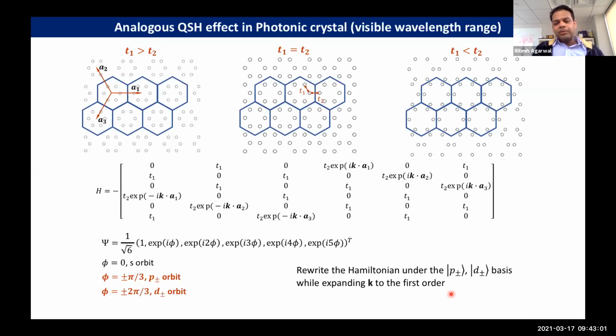in the photonics regime. So since we wanted to create polaritons, we knew, and there was no work prior to us, that we had to push this quantum spin Hall effect into the optical regime, which means visible light, the 500-600 nanometer regime, which is hard, not in terms of concepts, because these concepts are already derived, but from a fabrication perspective.